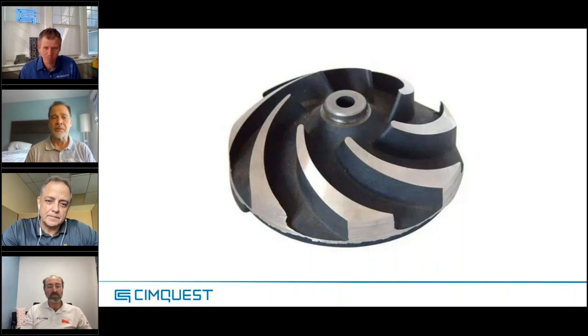I think this is a good example of an ideal part for our Meltio process. The size fits nicely in our smallest machine — you could put it in a bigger machine too and make multiples. Titanium is not a problem with wire-based DED. You'd print a near-net-shape and then CNC machine the fins and the hub in a subsequent step — maybe hone it for a nice cylindrical fit. Just guessing at the size, I think we could pump these out in about four hours at less than twenty dollars a part with our process.